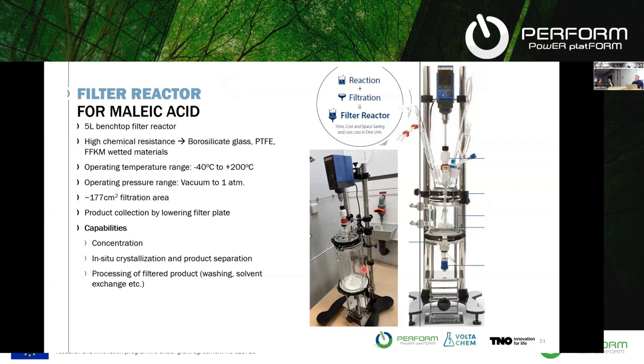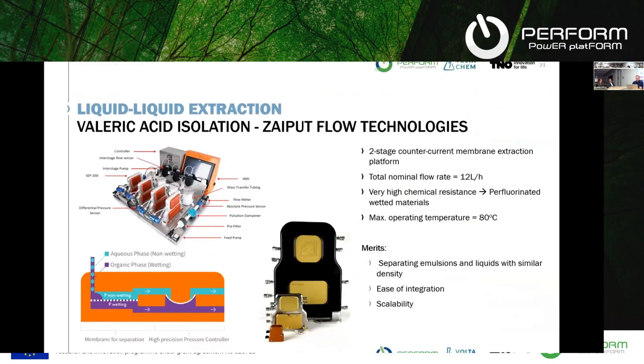We can lower the temperature so that we can cause precipitation of maleic acid. And because this is a filter, we can also wash the maleic acid crystals all in one setup. This is a really versatile and nice apparatus, and we will test it very soon.